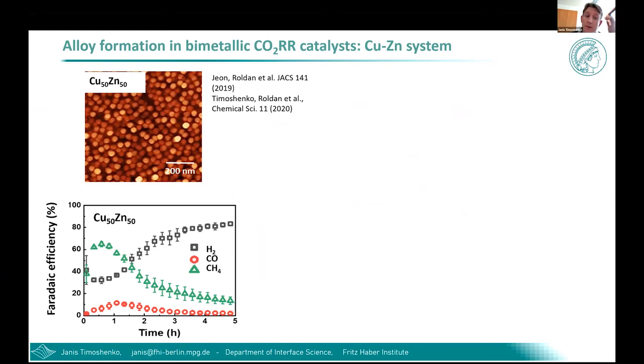Also, the importance of time-dependent structural changes in bimetallic CO2 electroreduction catalysts was highlighted in our own recent study of copper-zinc nanoparticles. Here we investigated size-selected copper-zinc nanoparticles with sizes of about 5 nanometers, and we observed quite an interesting time-dependent trend in their catalytic activity. Basically, reaction products after 5 hours were completely different from the reaction products after 1 hour under reaction conditions.